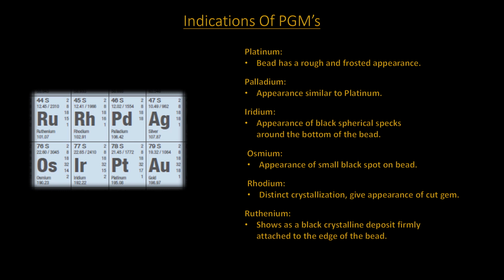If platinum is present, your bead will have a rough and frosted appearance. Palladium will present itself in a similar manner. Iridium, on the other hand, shows up as black spherical specks on the bottom of the bead, whereas osmium displays itself as a black spot on the bead. Rhodium has a distinct feature of crystallization, which gives the appearance of a cut gem. Ruthenium shows up as black crystalline deposits, which are firmly attached onto the edge of the bead.